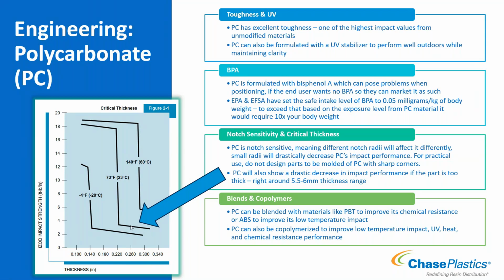It's also sometimes blended with ABS to improve its low temperature impact. As mentioned, ABS, because of the butadiene, has good low temperature impact. So I blend it with PC to get a PC/ABS with good low temperature impact, better than a straight polycarbonate.